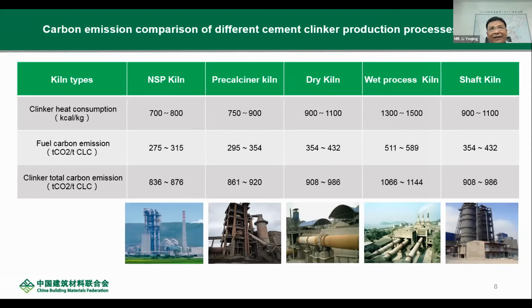The process carbon is similar. The power impact is also not so big, but the fuel emission reaches 600 kilograms. The total clinker emissions are close to 1,100 kilograms per ton clinker, which is higher than a lot of the NSP lines. The heat consumption of the shaft kiln is 900 to 1,100 kilocalories, and the clinker emissions are close to 1,000 kilograms.